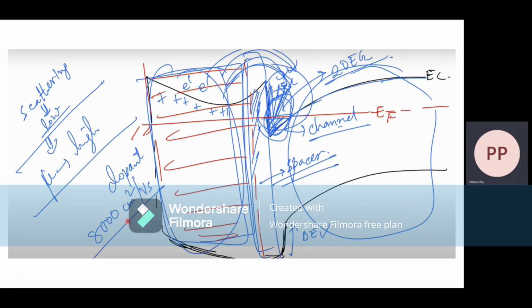I told you that at room temperature you can possibly get around 8,000 centimeters squared per volt second of mobility. This is the beauty, because you have an epitaxial interface, so interface roughness scattering is negligible, and the dopants are physically separated from the electrons by a few nanometers by the spacer layer. The spacer layer makes sure the channel charge is not coexisting with the dopant, because the gallium arsenide is not doped in this portion. So this is the basic structure of the gallium arsenide, aluminum gallium arsenide high electron mobility transistor, HEMT. This is a very important topic. You should understand this very carefully.